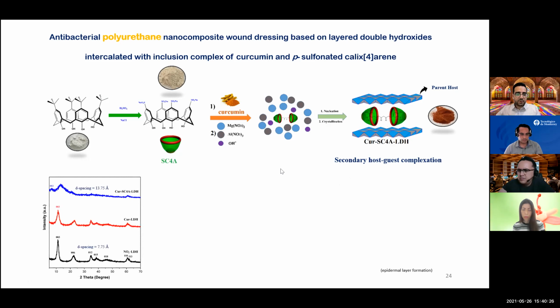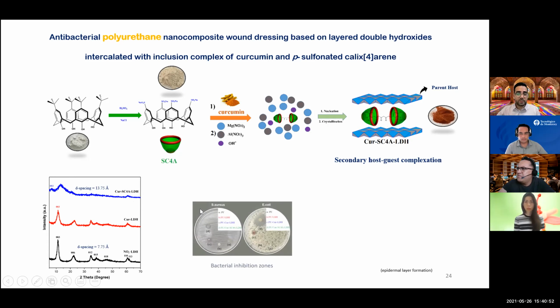You can see XRD analysis for those things. For example, for the LDH, the d-spacing is about 7.7. However, for the secondary carrier host-guest it is about 13.7. It means that the LDH has already been intercalated by those structures of the calixarene, and it shows that we can do it.